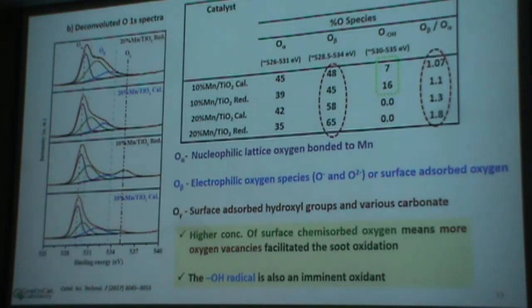Also, the surface adsorbed oxygen species, the chemisorbed oxygen species, play an important role in the oxidation reaction. But as you can see, in 10% Mn, although the ratio of electrophilic oxygen species is less compared to that of 20%, it still shows activity. That means there is also the presence of a hydroxyl peak at higher binding energy, which also acts as a good oxidizing agent, indicating that the surface adsorbed oxygen phases as well as the hydroxyl phases present in the 10% Mn play a role in the oxidation reaction.